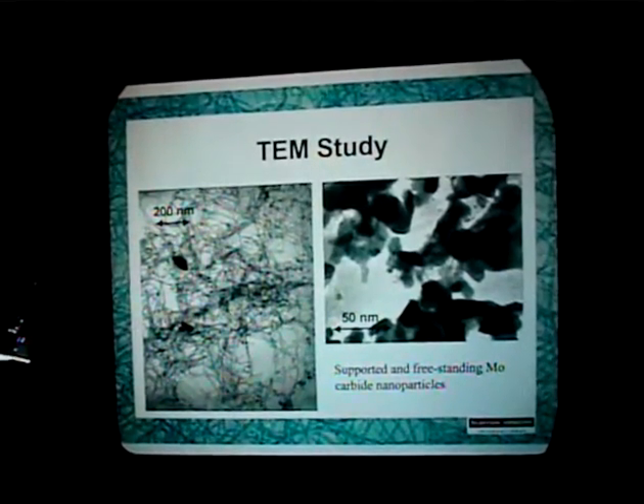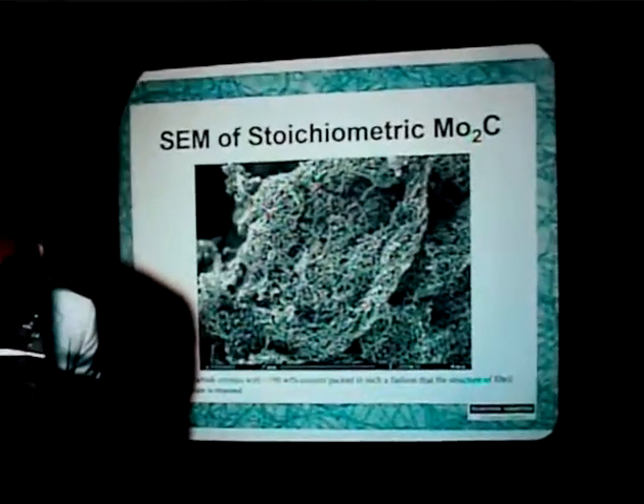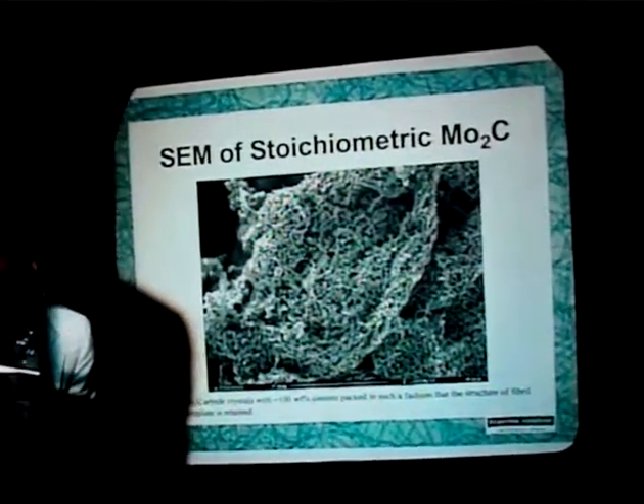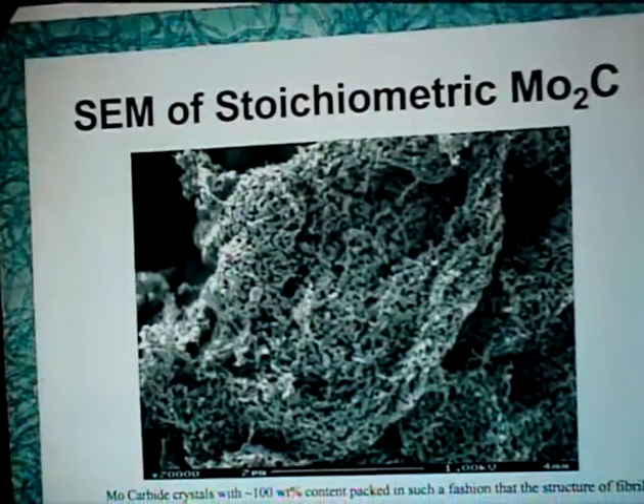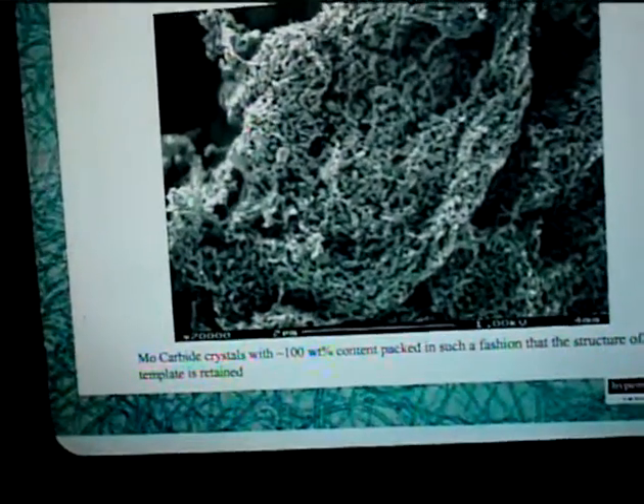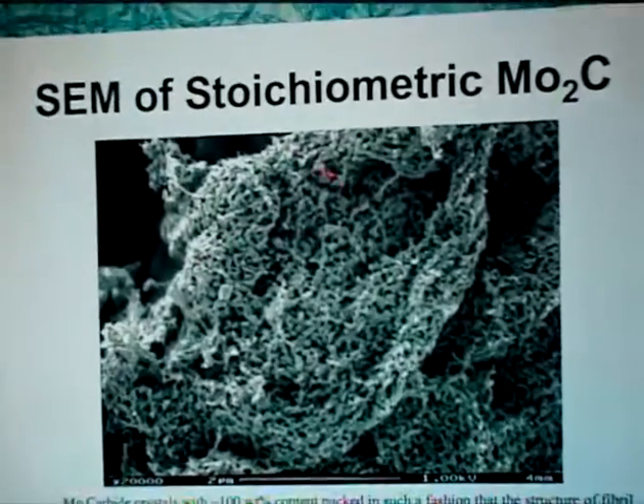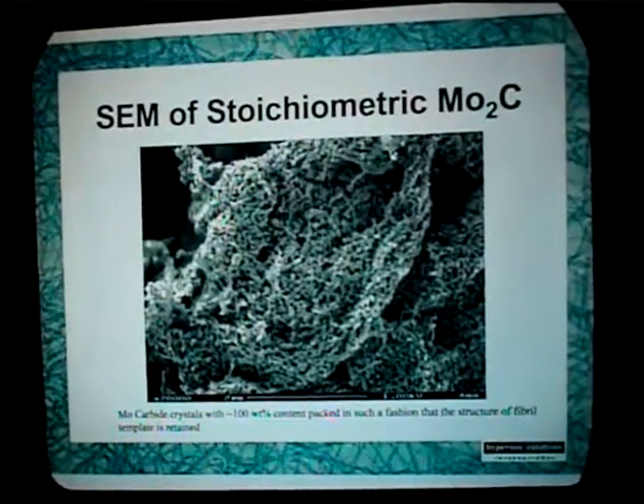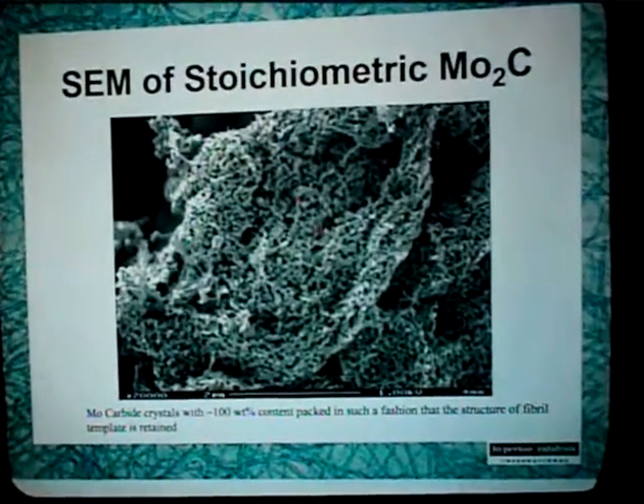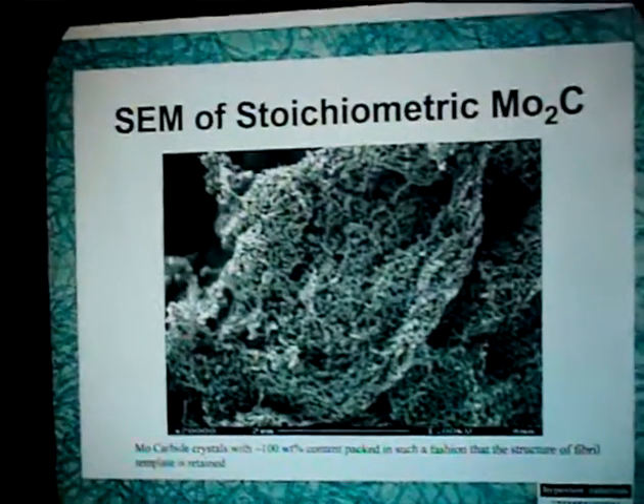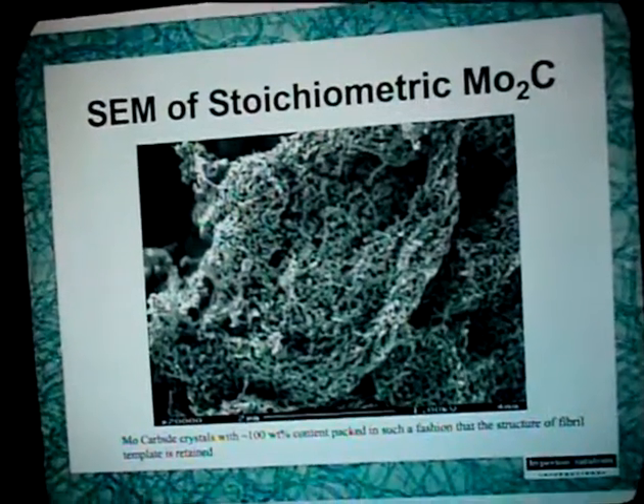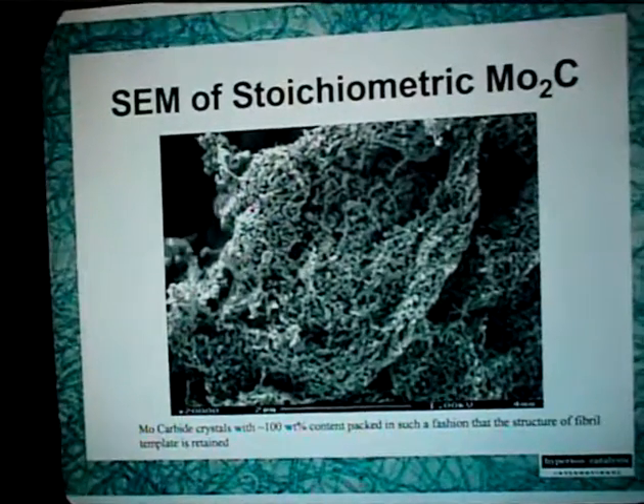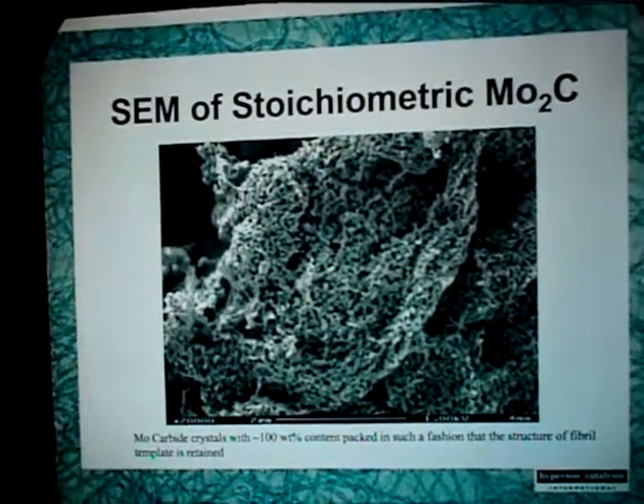We can also prepare a sample that is 100% conversion. So this is all molybdenum carbide. And again, you can see that on this SEM picture for a stoichiometric molybdenum carbide, that the final shape of the molybdenum carbide that you form is very similar to the one of the fibril that you start. So you can use the fibril as a template to make those materials.